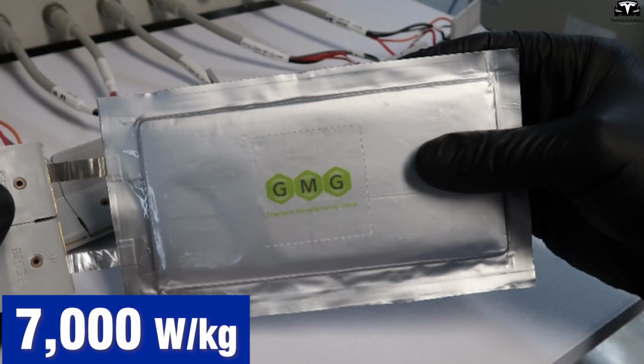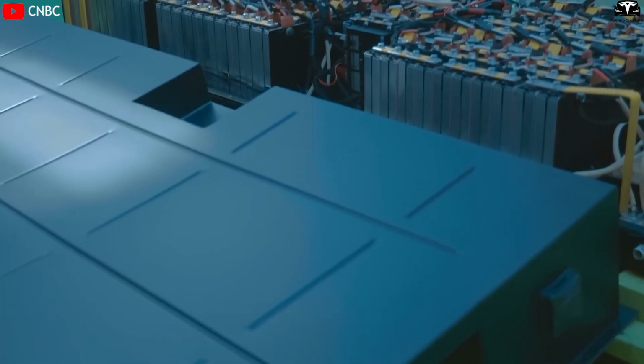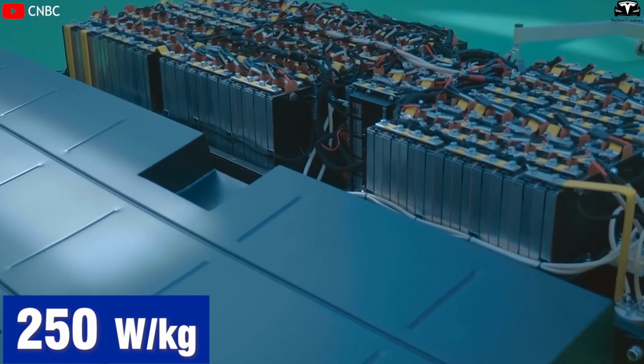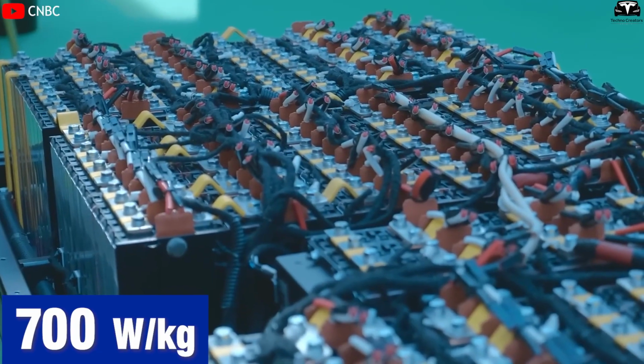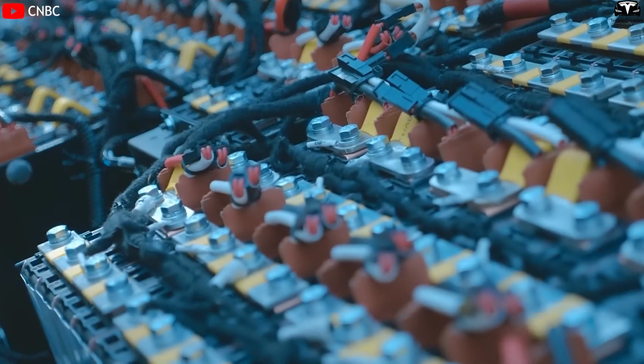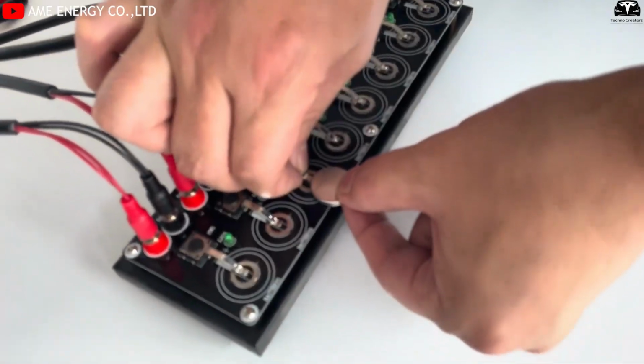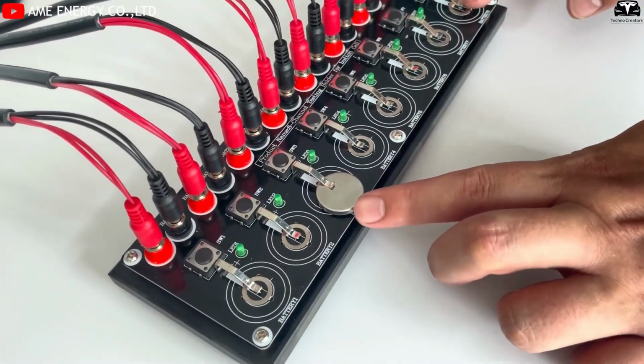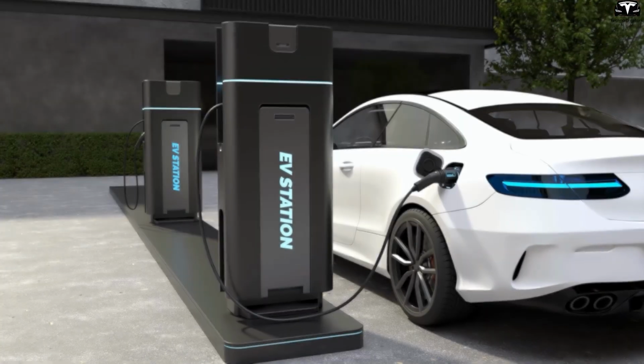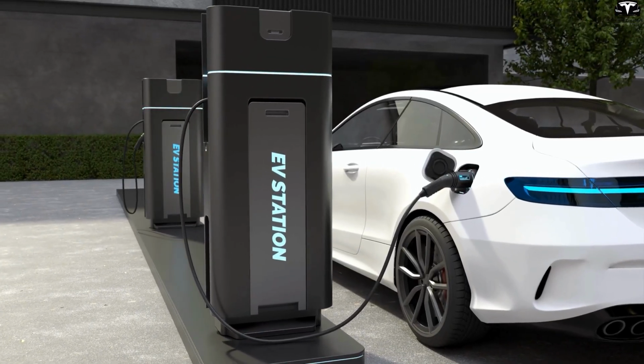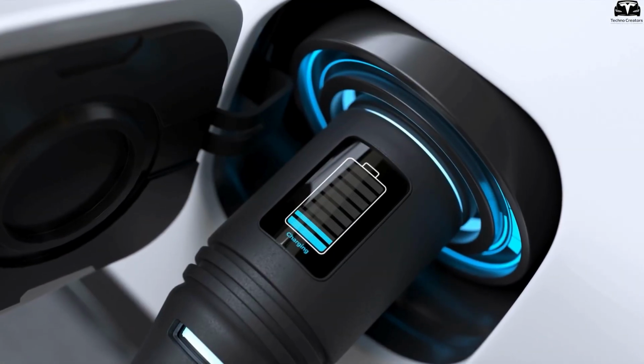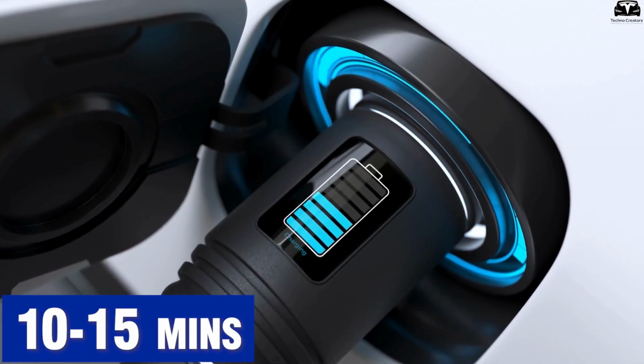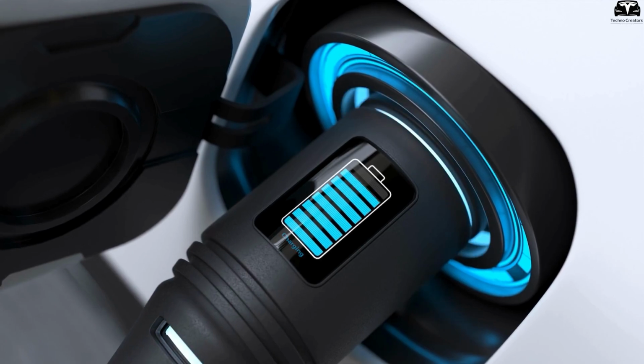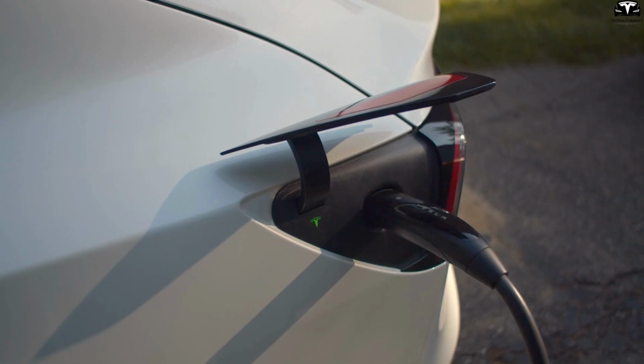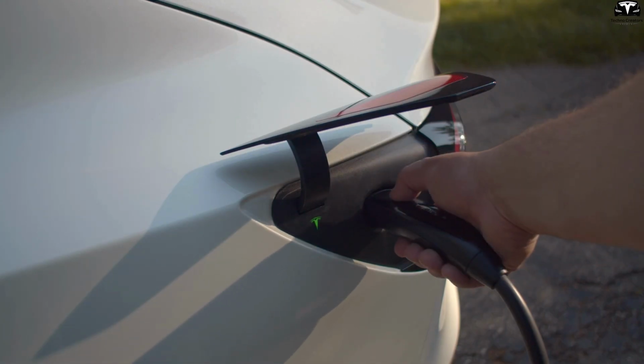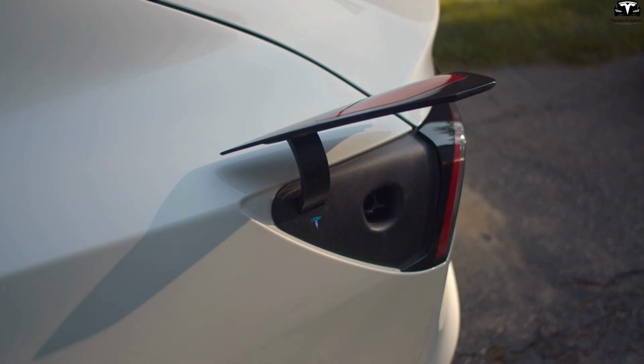One of the most remarkable features of graphene aluminum-ion batteries is their extremely high power density, up to 7,000 watts per kilogram, which is 10 times higher than conventional lithium-ion batteries' 250 to 700 watts per kilogram. This allows unprecedented charging speeds. In coin cell tests, charging times can be measured in minutes. If this speed can be scaled to automotive battery levels, it could fully charge an electric vehicle in just 10 to 15 minutes, something current lithium batteries cannot achieve.